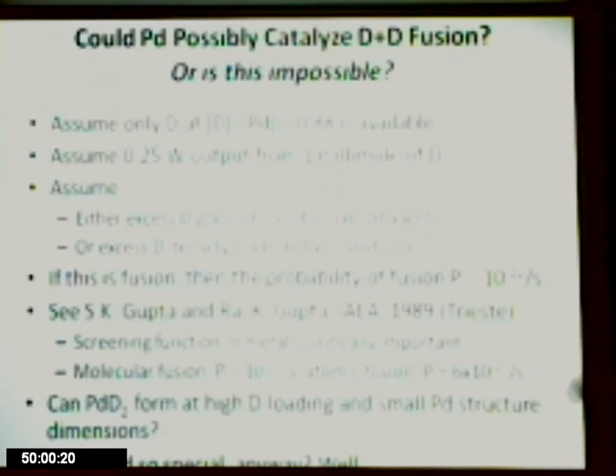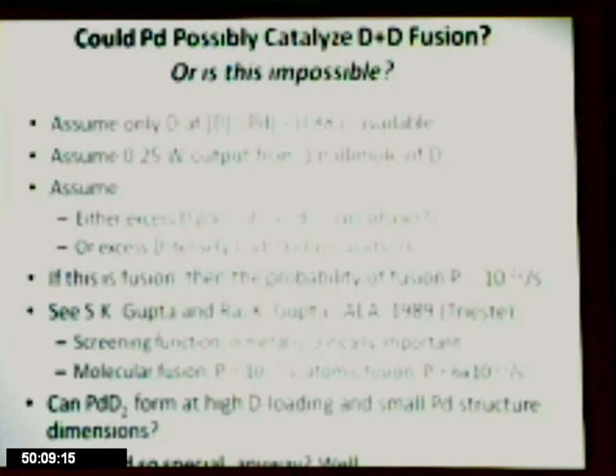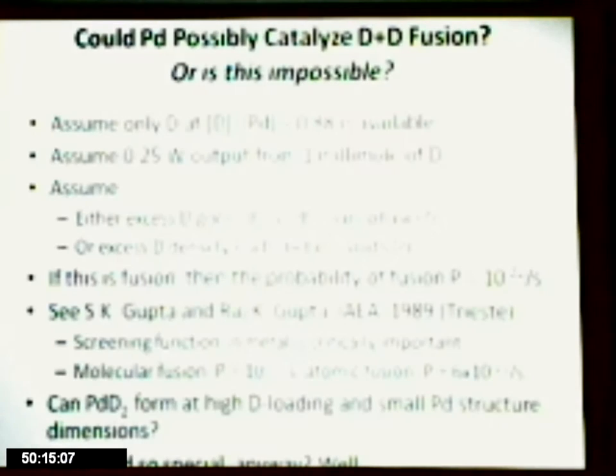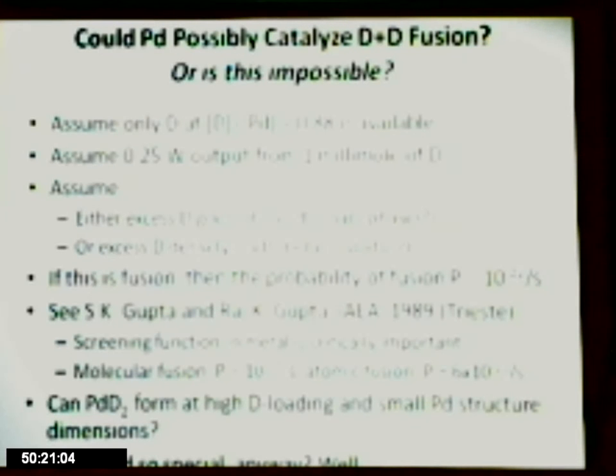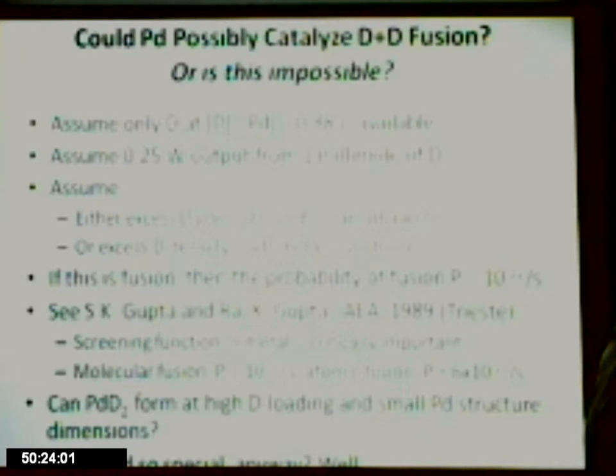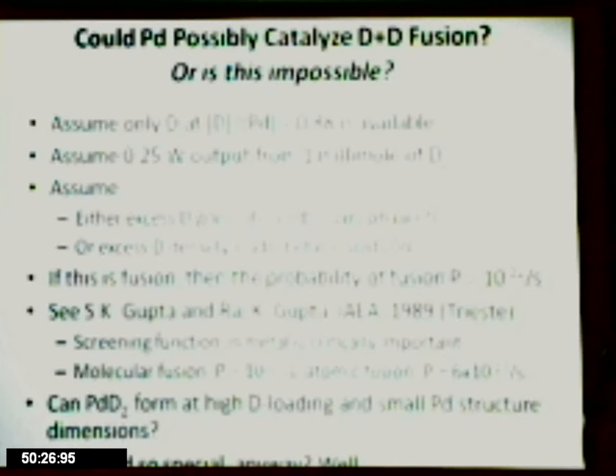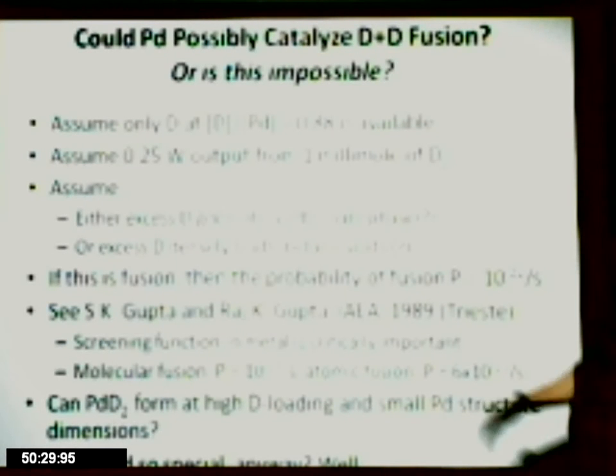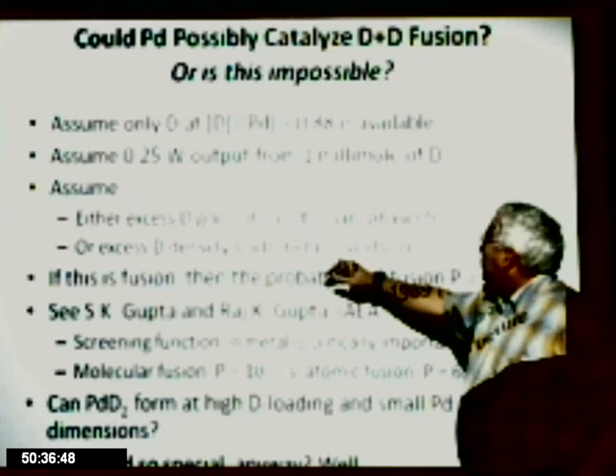Okay, just for some assumptions. This 0.88 rule: let's assume that for loadings less than 0.88, there's no effective deuterium to participate in whatever unknown process is going on. So we'll only consider deuterium on the sample that's above a concentration of 0.88. A typical value for these nanoparticles is about 0.25 watt output from 1 millimole of D2 absorbed on the palladium. And assume that either excess D goes into a PdD2 nanophase, or that the excess D densely loads metallic voids in these tiny little particles. You know, no idea what's going on.